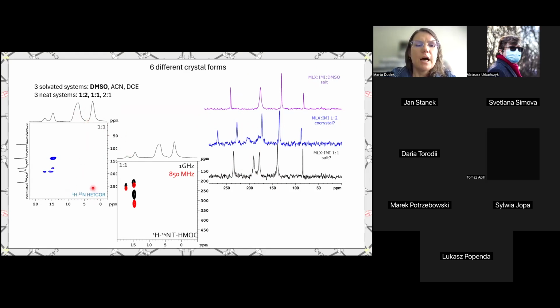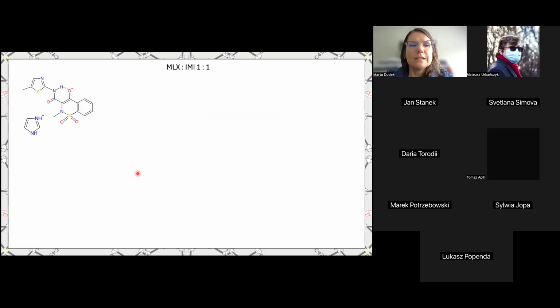This is nitrogen 15 HETCOR experiment. And these are two overlaid spectra from 1 gigahertz and 850 megahertz of HMQC proton detected nitrogen 15 spectra. And what we see here are 3 NH sites with different PQ values. And this can happen if we have a situation like this. So there are, as expected, two protonated nitrogens in imidazole molecule, and we have a NH proton. So there is no OH signal here, but NH proton on this meloxicam nitrogen.